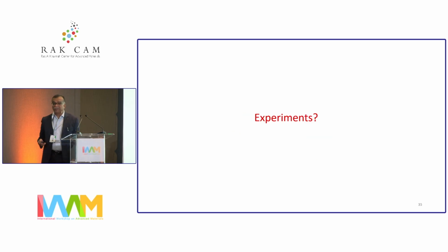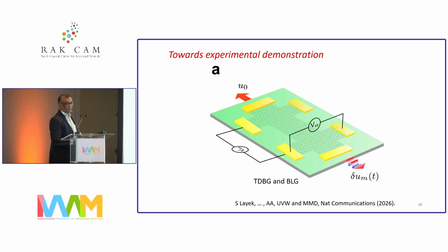Okay, what about experiments? And this is where Manda's group came back in. Unfortunately, they couldn't do exactly what we wanted them to do. So what he proposed is, instead of looking at natural vibrations of a lattice, he induced driven vibrations. This is the geometry: you have bilayer graphene, and these are the transverse electrode measurements, and the electric current is flowing along the x direction. And this is a driven vibration, so vibrational frequencies are very low, easy to measure in a circuit structure.